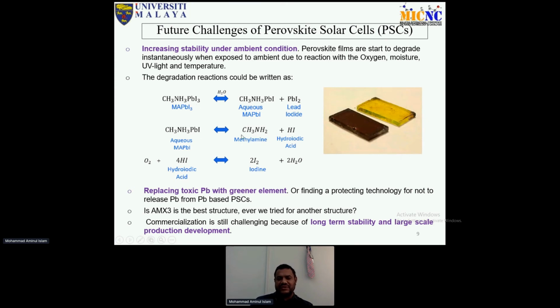And every reaction is basically two-way. Then again this decomposes and comes to iodide, and then this is the gas, and then goes to water. So you see over here, when you fabricate the perovskite on top of a glass substrate, primarily it's a black-brown color. After it degrades, it comes to this, which is only a yellowish color. Basically, this is the lead iodide. On top of the glass, only the lead iodide is remaining over here. And the lead iodide color is, of course, yellow.